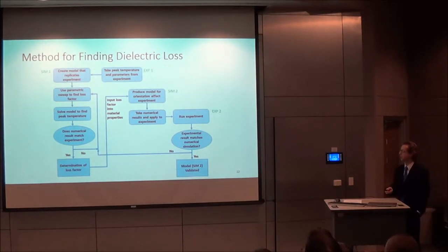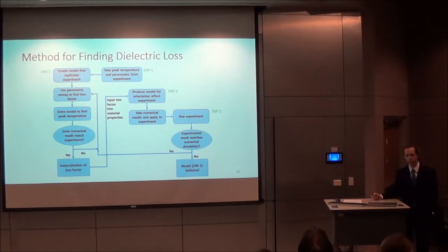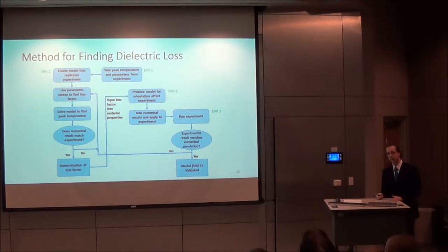This just illustrates the approach for finding the imaginary dielectric loss of cordierite, which is an arbitrary dielectric material that was chosen to model and experimentally evaluate the orientation effect for microwave heating. And so this is the approach that was used. First, a model was created that replicates the heating experiment that was conducted. A parametric sweep is run to find the loss factor based on a final temperature that is known, which temperature is solved for, and then we check if the numerical result matches the experiment.